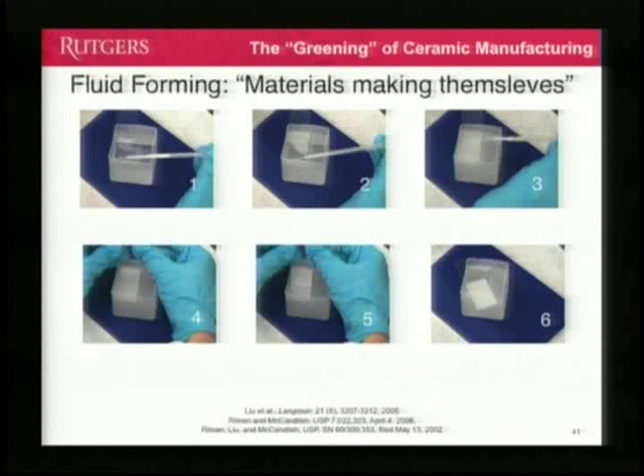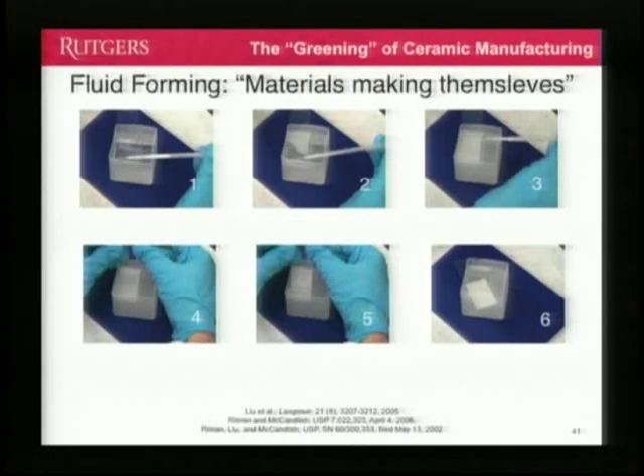So this is a material called lead zirconate titanate. And the alcohol inside this dropper, when it hits the water, spreads. And when it spreads, it delivers the particles to this raft. So think about this as like the bubbles, you know, when you're taking a bubble bath, how they like to assemble on the other side of the bathtub and form beautiful hexagonal arrays. Now we have these particles packing themselves into dense arrays, and if we put a glass slide into there, we can actually pull this material right off of the water to make a beautiful monolayer film. And so here's an example where we use industrial aluminum oxide and show we compact these materials beautifully as a single layer of particles.